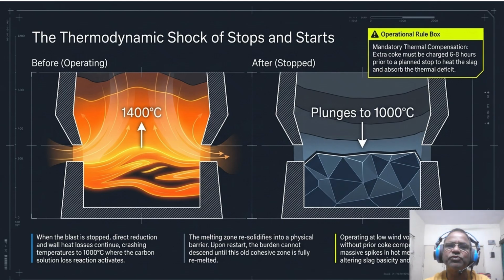And this is why the operational rulebook is so critical. Extra coke must be charged 6 to 8 hours prior to a planned stop. Operating at low wind volume during a start without this compensation triggers massive spikes in the hot metal silicon and fundamentally alters the slag basicity also. So you are essentially trying to restart a frozen engine without oil. The friction is purely thermal. So for longer stops, we move beyond simple compensation into the complex world of blow down and blow in.